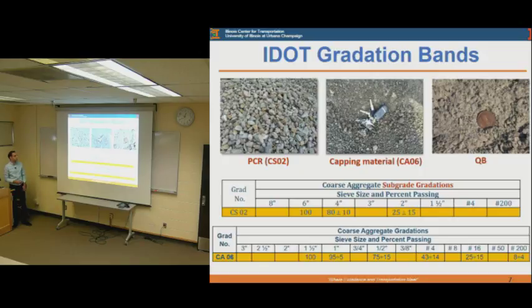So there are several gradation bands. The two that are of concern in this study are the CS02 gradation band, which is the large aggregates that are mainly larger than 2 inches in size and can be up to 6 inches in size. And there's the CA06 gradation band, which is a dense graded typical base course or sub-base material. It has a top size or maximum nominal aggregate size of 1 or 1.5 inch, and 4 to 12% fines material passing number 200, and we're trying to investigate using higher than the 12%, 15%